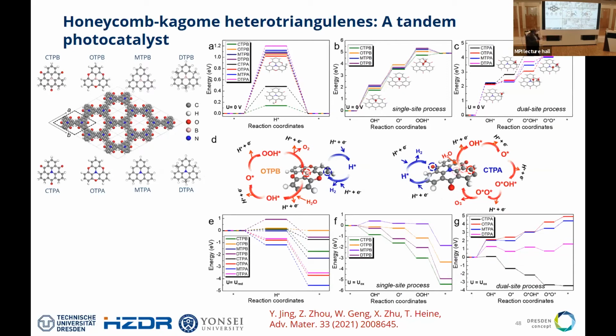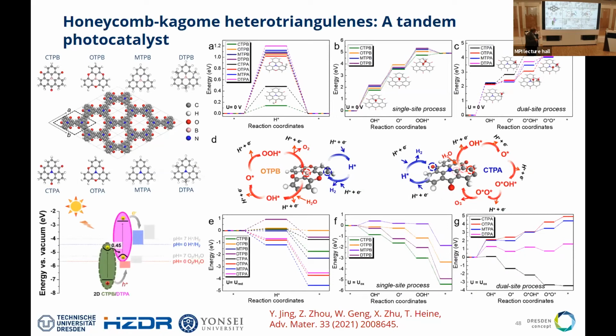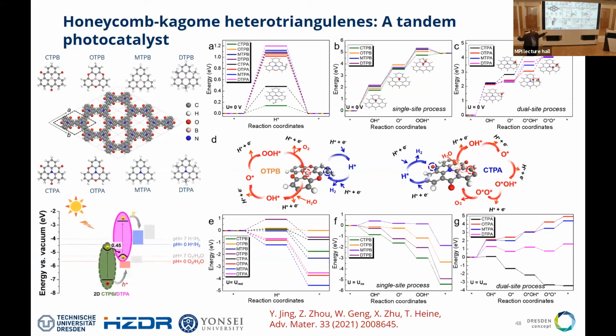And if one is doing that, one really can show that if you pick the right of these polymers, you can implement a very interesting device. Namely, you couple the photocatalyst in 2 electrodes. On one side, you harvest a photon, right, from a flat band. The electron goes to a very conductive band. And without overpotential, you have the oxygen evolution reaction. Then you just link the one electrode with another electrode electrically. You even gain a little bit of energy, so half a volt. And then you harvest a second photon, right? And you move it up here, and there you can run the hydrogen evolution reaction without overpotential, and you would have basically a tandem device for photocatalysis. So that means you can bring these very interesting polymers also towards an application. Good.